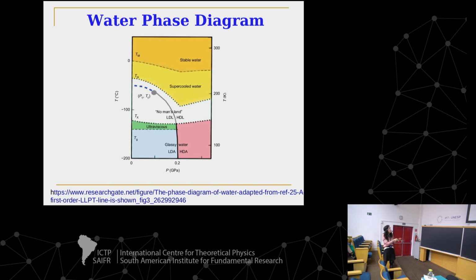Another thing people are doing is that they go, you see the critical point has this dashed line here, okay? Because imagine, if I get to the critical point the specific heat diverges, when I get close, it has to have a peak. You understand? No, nothing goes from smooth to divergent. Nature is, the Gibbs free energy doesn't work like that. So we know that if there is a divergence here, around here there will be peaks. Okay? And if I see huge peaks crossing there, I can get.